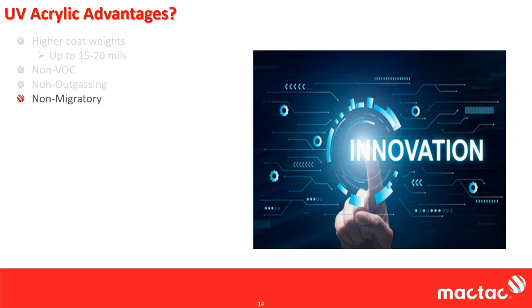In fact, a lot of times these devices are sealed so that you can drop them in water and they're not destroyed. So whatever's getting outgassed is going to stay in there. It's going to condense, and it's going to condense on that very delicate printed circuitry that's in there. And if you have a lot of unreacted monomers that typically exist in solution-based adhesives, that does eventually eat away at that circuitry, and then you start getting antenna failures or certain different failures in there. You start degrading circuits.